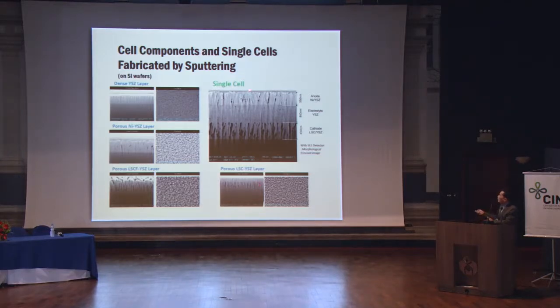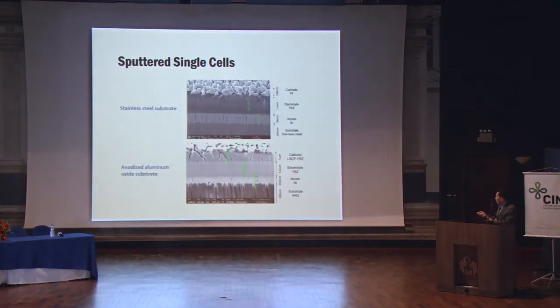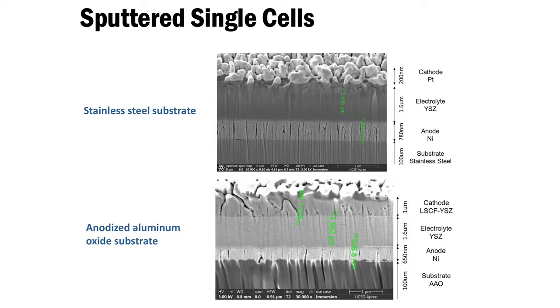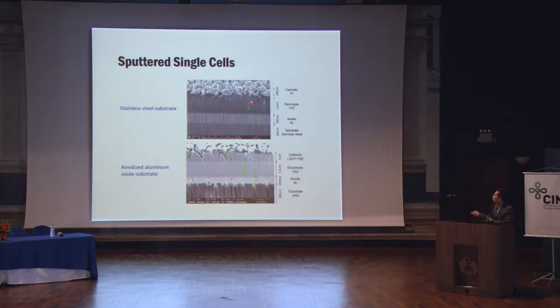So this is a whole complete cell deposited on the silicon wafer, and you can see here we have a fully dense electrolyte, yttria-stabilized zirconia electrolyte, a porous nickel YSZ anode, and then also a porous LSC cathode. And then we move on to demonstrate the deposition of the sputtered cell on a stainless steel substrate. And here, again, this is the stainless steel substrate, the nickel YSZ anode, the electrolyte, and in this case, we have a platinum cathode.